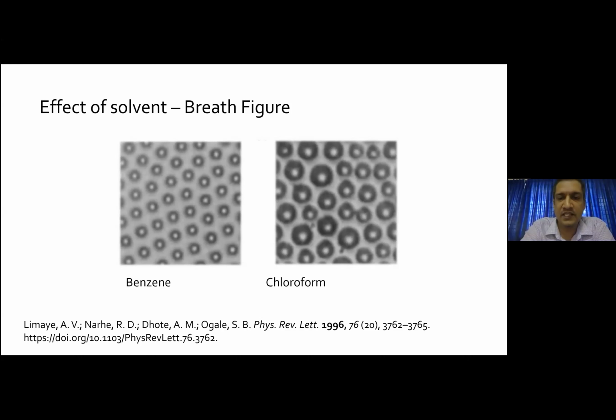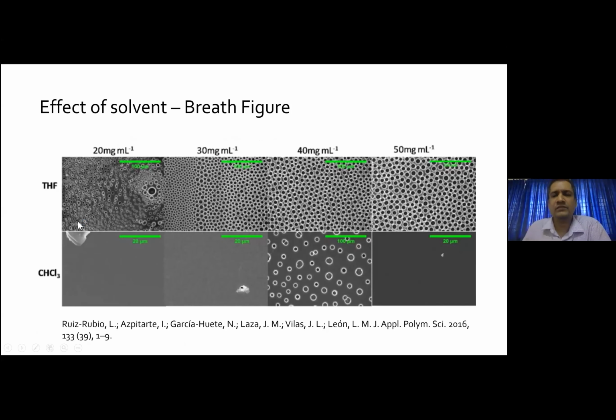The difference between benzene and chloroform is that benzene has a very low density compared to chloroform, plus the rate at which the droplet forms in the case of benzene is much slower than the rate at which the droplet forms in chloroform. Because of that, a bimodal distribution of pores is formed in chloroform. Here, the comparison is done at 70% relative humidity for benzene and chloroform.